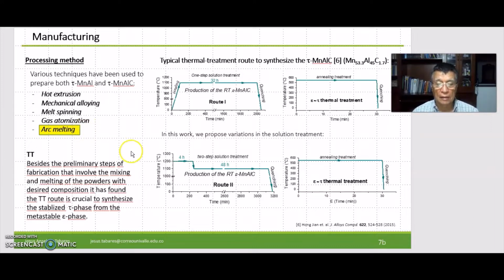Hong-Jian described a thermal process for the synthesis of the epsilon phase. After the solution treatment finishes, the alloy is quenched in water to retain the epsilon phase at room temperature, and the room temperature epsilon phase is annealed for several minutes at a temperature that varies between 500 and 700 Celsius degrees, to induce the epsilon to tau phase transformation.